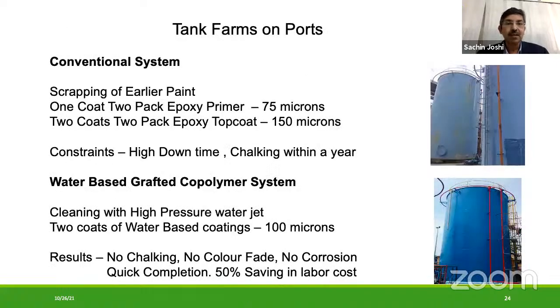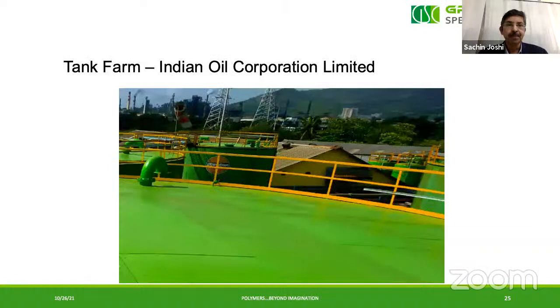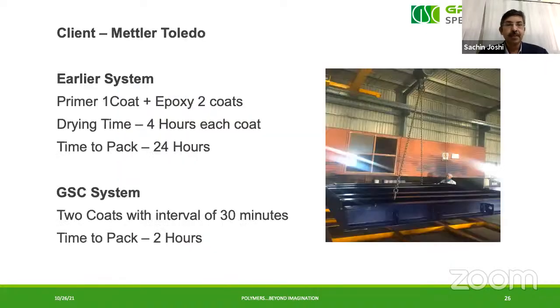We have done tank farms and port, Malaysian port. It's a bio fuel tank. Coating system was 1 coat of primer, 2 coats of epoxy, and then high downtime, chalking within a year. So you can see we have not removed the earlier coating. We just cleaned it with little sanding and high water pressure jet, 2 coats, and absolutely it is 3 years as it is. We have done Indian Oil Corporation, Bombay. We have done a tank farm top coating. We have done with this coating only 2 coats, 100 micron. Still, it is going strongly.